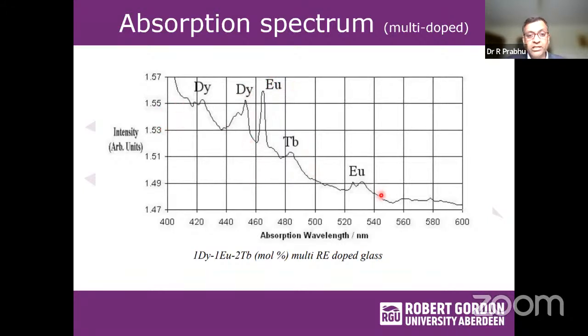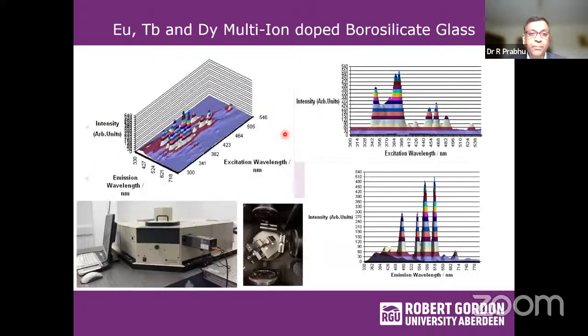And in the combined form, you still have the strong absorption bands of dysprosium, europium, and terbium inside the glass. So this is the typical signature from a multi-doped glass using Eu, Tb and Dy. You can see this is the 3D excitation emission spectrum, and this is the excitation spectrum for this multi-doped glass. It has a broad excitation in the near UV, ranging from 350 to around 400, 410. And very sharp emission bands, which are specific to each of those rare earth elements doped inside. So this is for Eu, this is for Dy, and this is for the Tb. So you have specific emissions, which are characteristic emissions from these rare earth elements. So in principle, we have developed a multi rare earth doped spectral signature in borosilicate glass.